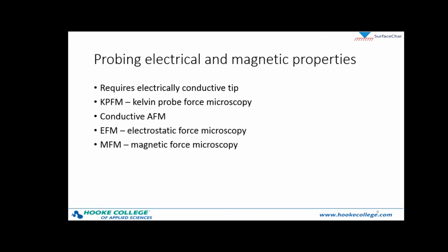Often these modes also require the ability to image your sample in two passes, one to collect the topography and a second one at a slight elevation of a few tens of nanometers above the sample to probe the electrostatic or magnetic interaction. We'll start with Kelvin probe force microscopy, or KPFM, and then I'll review conductive AFM, electrostatic force microscopy, and magnetic force microscopy.